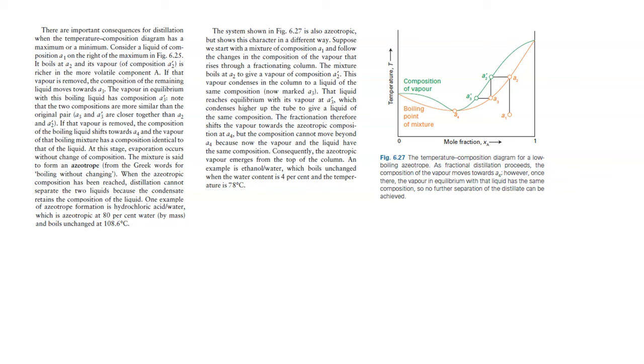The mixture is said to form an azeotrope, which is from the Greek word for boiling without change. When the azeotropic composition has been reached, distillation cannot separate the two liquids because the condensate remains the composition of the liquid. One example of azeotropic formation is hydrochloric acid in water, which is azeotropic at 80% water by mass and boils unchanged at 108.6 degrees Celsius. The system shown in figure 6.27 is also azeotropic, but it shows the character in a different way.